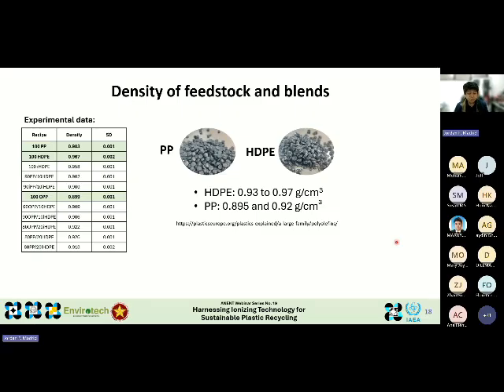As many of you may already know, high-density polyethylene has a more linear molecular structure compared to polypropylene. That's why HDPE is generally reported to have higher density compared to polypropylene, which has a more branched structure. When we measured the density of our feedstock, including the HDPE, polypropylene, and the OPP sourced from Envirotech, the results were very consistent with what is already reported in the literature and with values typically used in industry.